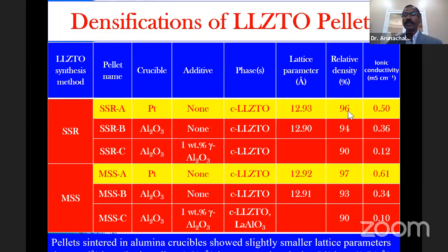The relative density was well above 95%, so it very well qualifies to be made into a full cell. The lithium ion conductivity is about 0.5 and 0.6, again what has been reported in the literature. Compared to that, the other pellets had relatively lower density. The reason why we added alumina is mainly to ensure that the density is improved. That has been documented very well in the literature.